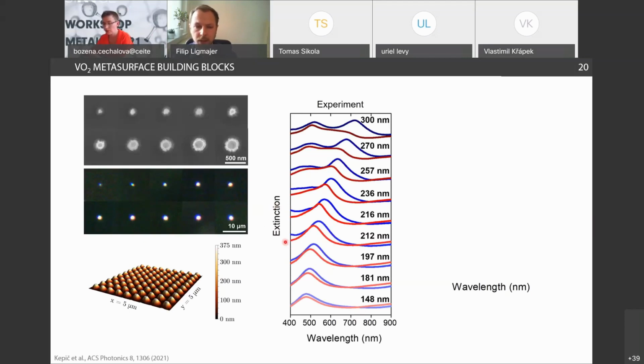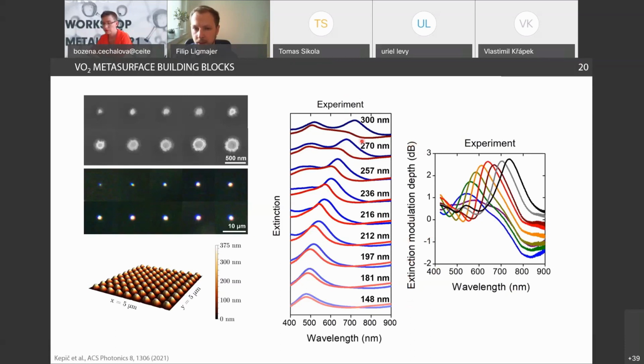and we then measured their extinction, that is related to scattering, of course, and we indeed observe that if you switch VO2 from room temperature to the high temperature phase, you observe quite a significant change in the optical properties. In order to evaluate this switching or tunable behavior, we introduced an extinction modulation depth, that is some sort of metric or figure of merit that tells you how large the difference between the two states is, in decibels. And you can see that based on the size of your disk, you can of course achieve quite nice modulation depths across the whole visible and near IR range.